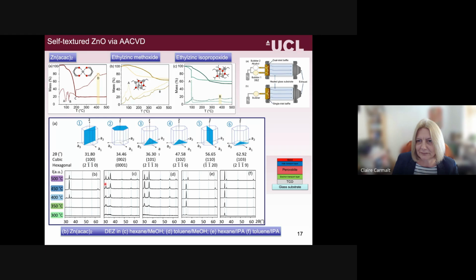And it's interesting when you look at the XRD because you get very different results depending on the precursor. So when you use zinc acac, you don't get much, it's not very crystalline at low temperatures. And then you can see that you're getting preferred orientation. These crystal planes shown here relate to the crystal planes in zinc oxide, starting from this side going across. And so you get preferred orientation in the 002 plane shown here.